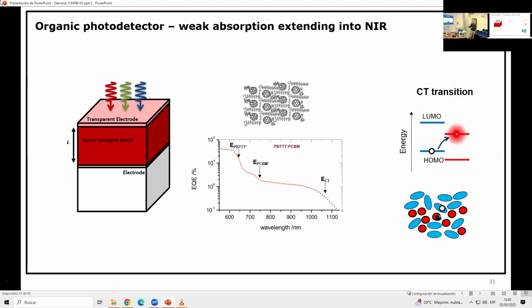It actually comes from these transitions. If you mix 2 materials, you have optical transitions from HOMO to LUMO on the same material, which would be like this or like this. But an infrared or a more redshifted transition goes from the HOMO of one material, kicking it into the LUMO of the other material. You see, energetically, it's a redshifted transition. It's not very likely because the molecules are away from each other, so the chance is not high. But it does happen. And we know it's this transition because if you change the donor or the acceptor, this band is shifting up and down, and it's not there in the neat materials. So this charge transfer transition is what gives this very weak absorption here.